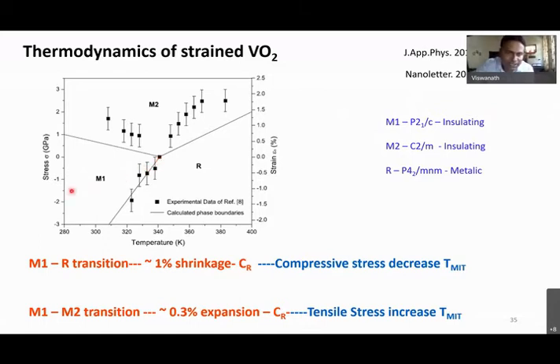But if there is a stress, for example compressive stress acting, then the transition temperature keeps on decreasing. Same way, if there is tension, the tension is prone to induce the phase transformation from M1 to M2. M2 is crystallographically different, with a different space group, but it is monoclinic, and it is also insulating. So the M1 to M2 transformation can be induced if you apply tensile stress, and M1 to rutile phase can be induced if you apply compressive stress.